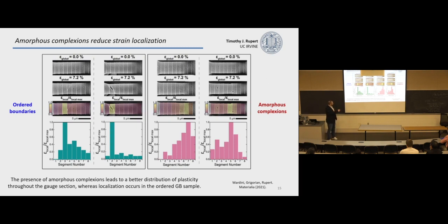But the point is, for the sample with the ordered grain boundaries, you get very localized strain. So once you start to plastically deform, it localizes and the sample breaks. And we can compare that with the sample with the amorphous complexions. We have much more distributed plasticity, and we can get a more homogeneous deformation.